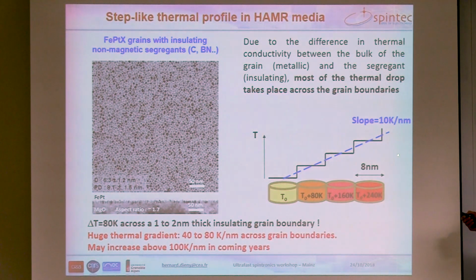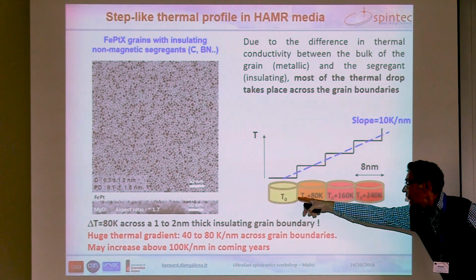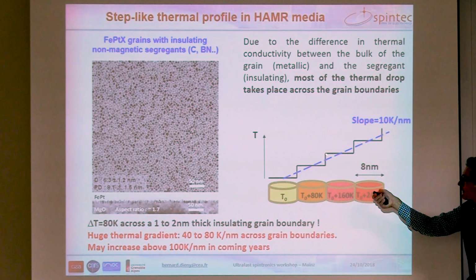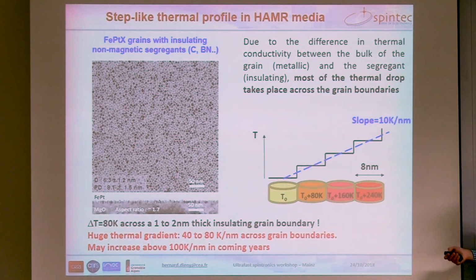So if we have an average slope of, let's say, 10 Kelvin per nanometer, and we assume the grains are 8 nanometer in diameter, it means that every time across the grain boundary, we have a temperature difference of 80 Kelvin. Since the grain boundaries are 1 to 2 nanometer thick, these steps correspond to thermal gradients of the order of 80 Kelvin per nanometer. So it's really huge.